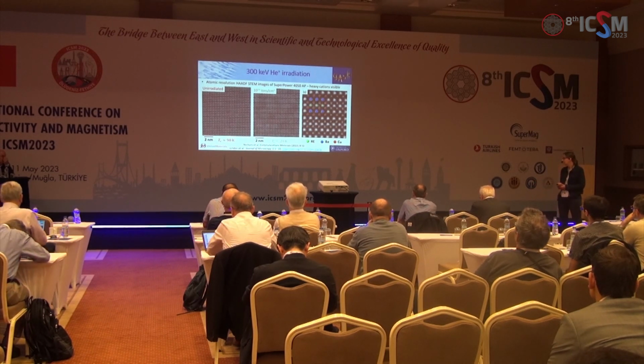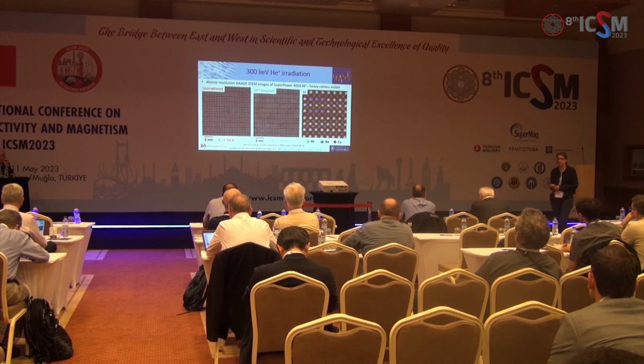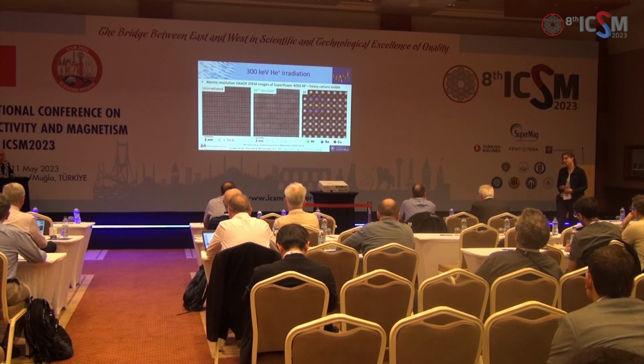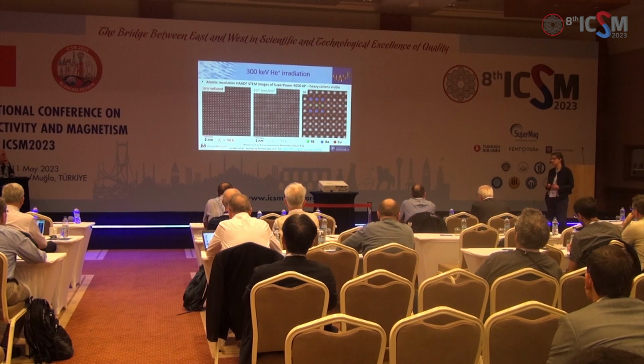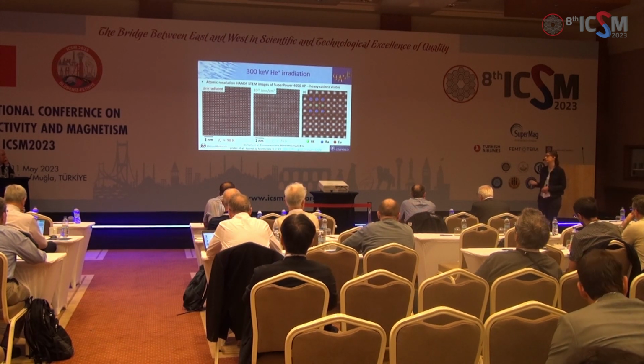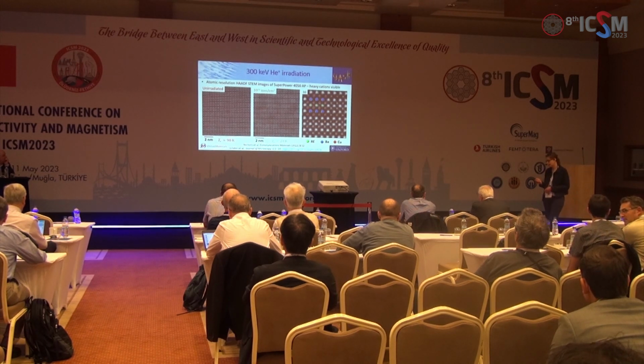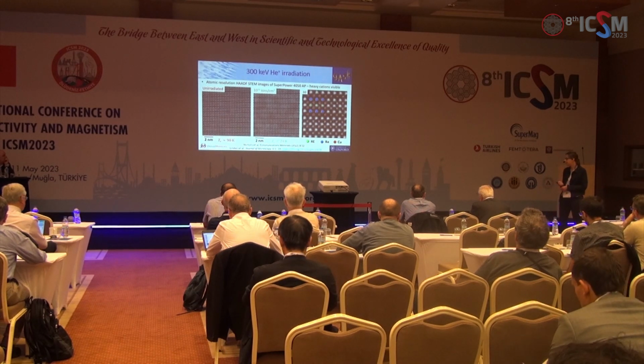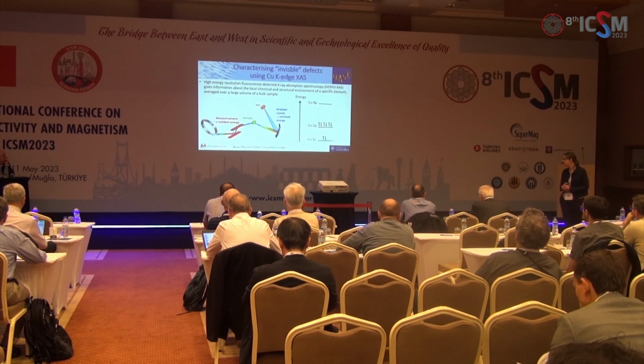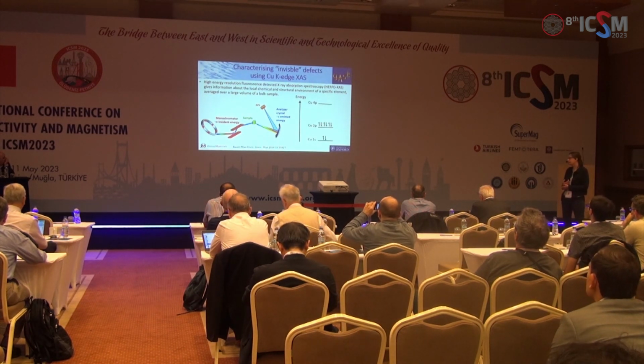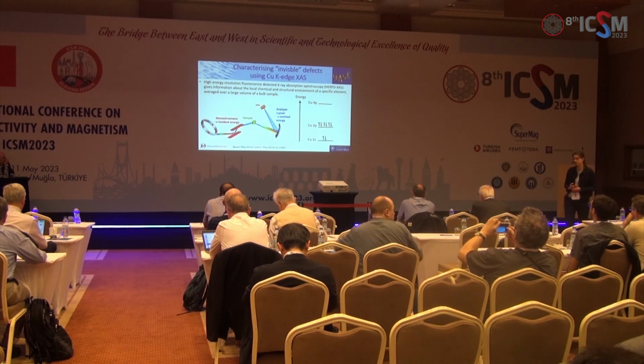So we started thinking that maybe, and a lot of the literature has mentioned this already, that the oxygens can move around much more easily than the cations. And so probably the damage that's causing the TC degradation is because of oxygen defects. And we can't see that, certainly in this imaging mode of the TEM, and it's pretty difficult to see it in any imaging mode, actually, those oxygens, when you've got such heavy cations in close proximity. So instead of doing electron microscopy, we've looked at other techniques where we can get some handle on what's going on with the oxygens in the structure.